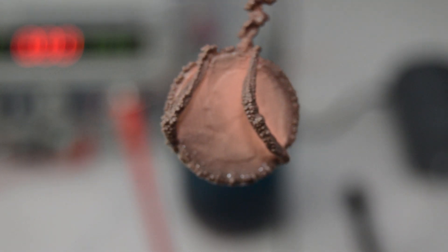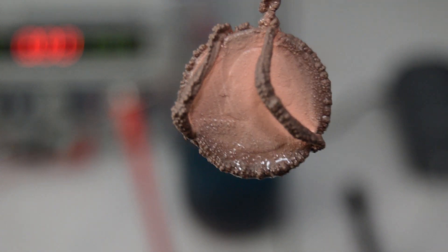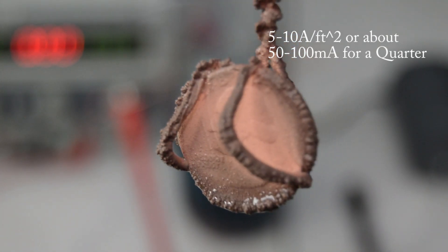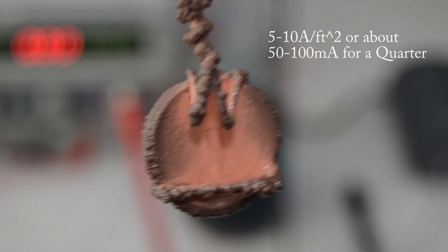The plating results at 830 milliamps were not good at all. For a bath with this chemistry, it's better to keep plating current density to about 5-10 amps per square foot, which all that really means is that it's better to plate slower for longer with a weaker acid solution like this.